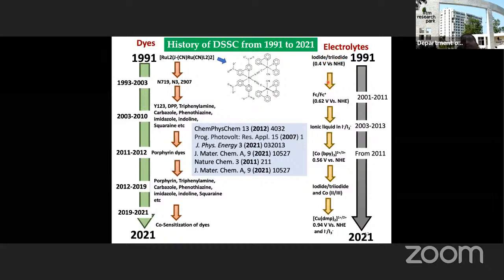Compared to iodine triiodide, ferrocenium has 0.6 volt, meaning it is even closer to the HOMO of the dye. Similarly, ionic liquid-based iodine triiodide systems were explored, and then cobalt bipyridine-based complexes, which is almost like ferrocenium, about 0.56 volt, just above ferrocenium. Other is copper dimethyl pyridine based complex, about 0.94 volt with energy, very close to the HOMO of the dye. That means if you use copper-based system, you will get more voltage, meaning more energy harvested. Energy is the charge that is flowing multiplied by the voltage that you get in the cell, so Q into V equals energy, in electron volts. So more energy can be harvested only if the voltage is high. High voltage can be obtained by copper, to some extent by cobalt, not by iodine triiodide.